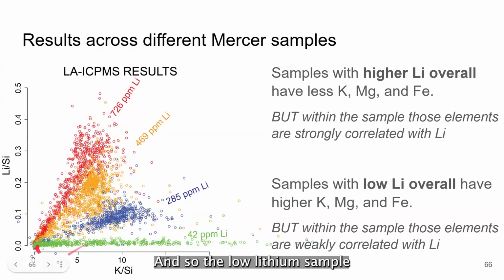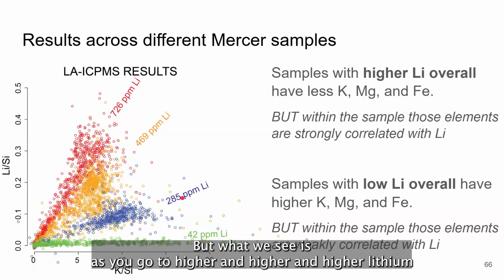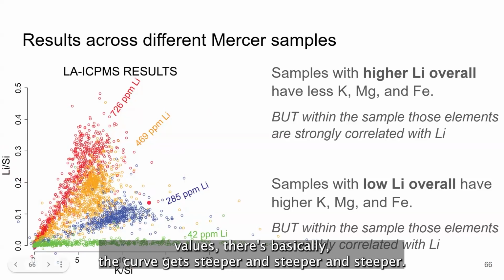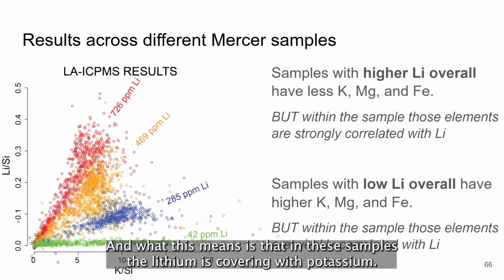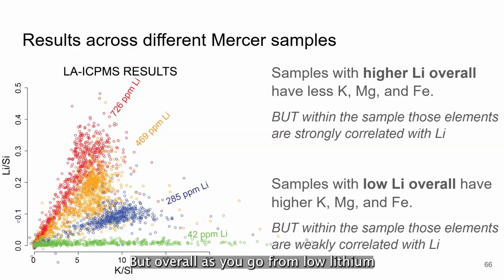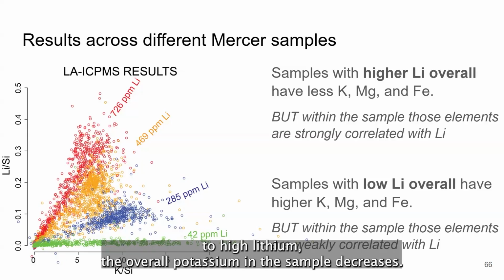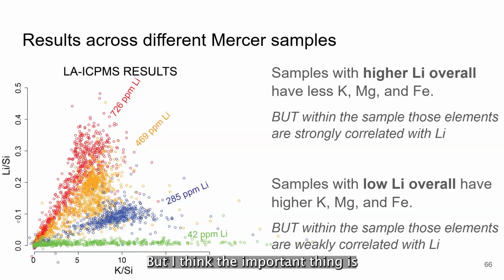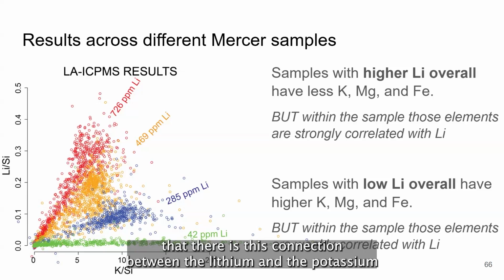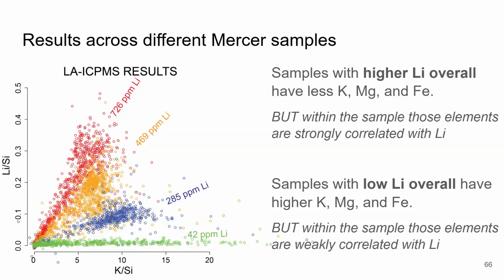And so the low lithium sample has low lithium also in the LA-ICP-MS. But what we see is as you go to higher and higher lithium values, the curve gets steeper and steeper. And what this means is that in these samples, the lithium is covarying with potassium. But overall, as you go from low lithium to high lithium, the overall potassium in the sample decreases. But I think the important thing is that there is this connection between the lithium and the potassium.